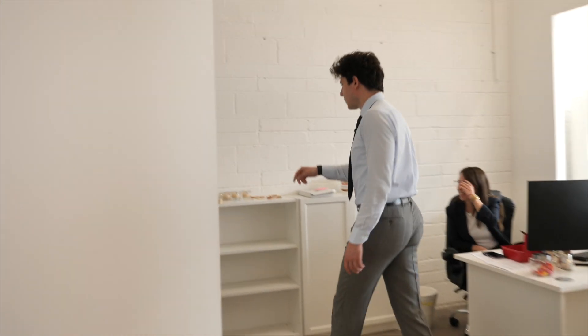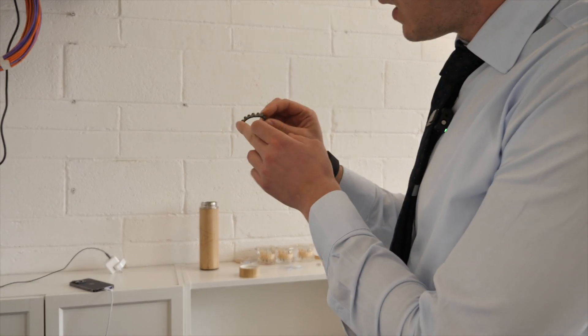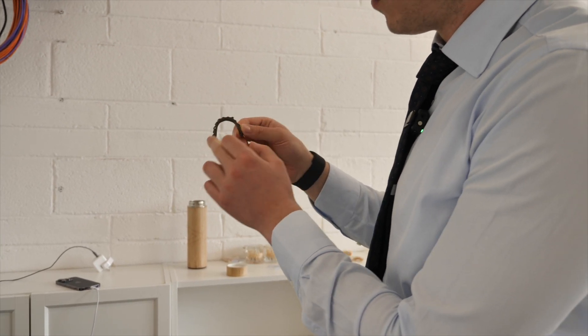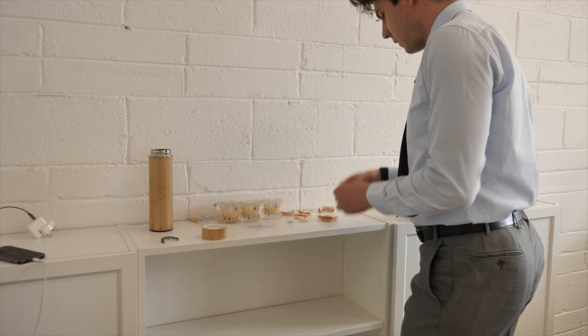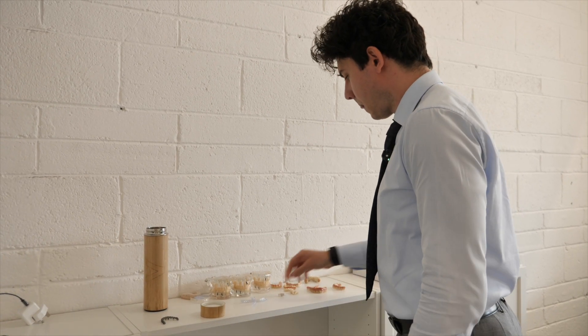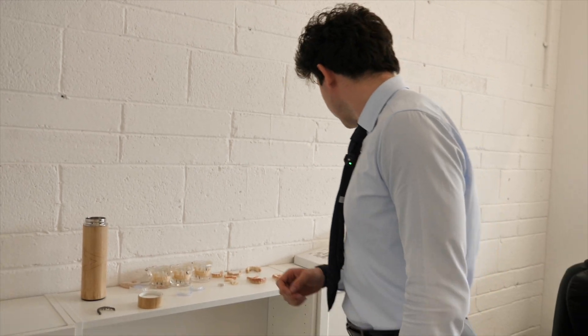We have some examples here. This is titanium - you can see it's machined and polished on the fitting surface, but where the zirconia needs to be bonded on top, it's roughened to improve the bond strength of the veneering material. We've also got various zirconia teeth - this is monolithic zirconia with gums and teeth. These are printed; we were in the printing room earlier.